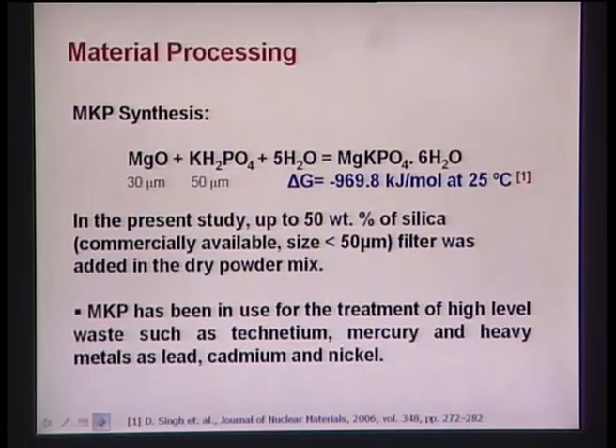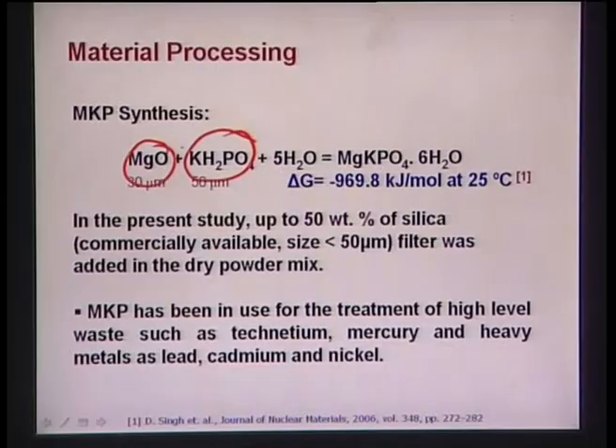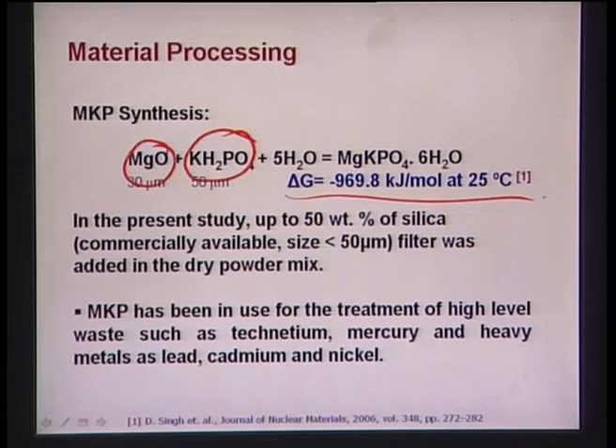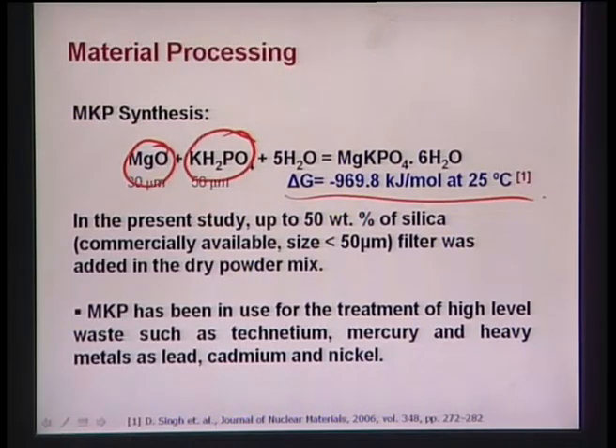The material is prepared starting with precursor powders: magnesium oxide and KH₂PO₄ mixed together in an aqueous solution to yield hydrated magnesium potassium phosphate. The delta G value is largely negative — approximately minus 970 kJ/mol at 25°C — confirming the reaction is thermodynamically feasible. You can start with fairly coarse magnesium oxide particles and mix them together.